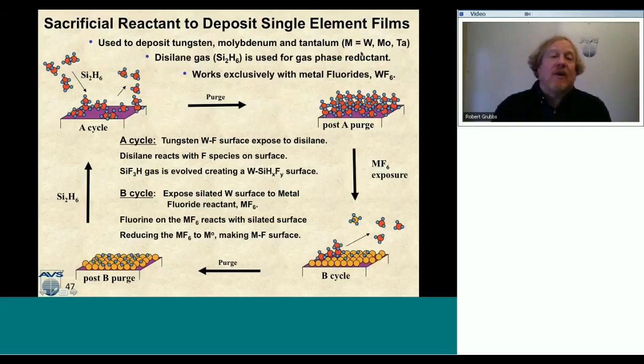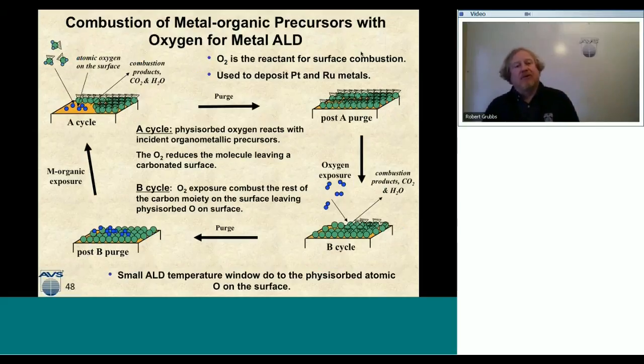Now let's go to another way to deposit a single element, and that is the combustion reaction of organometallic precursors with oxygen. And this is really my favorite way of depositing because I just have so much interest and respect for the chemistry. So we'll talk through it. So I have a surface right here, and I have some oxygen on the surface that's in a physisorbed state. So mind you, if it's a physisorbed state, it has a very low temperature window. And when I bring down an organometallic precursor, it'll react with this physisorbed oxygen and combust. It'll actually make carbon dioxide and water and bond with the surface.